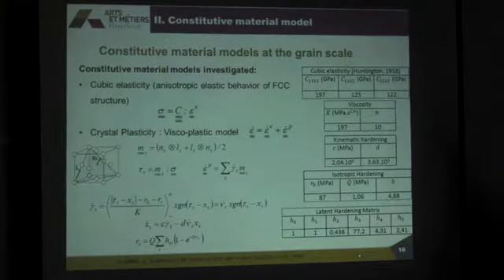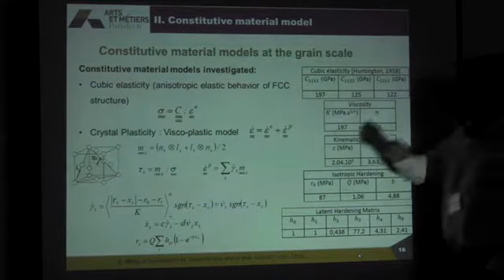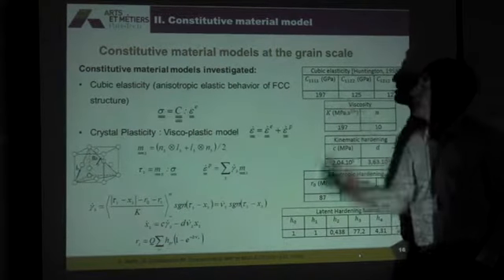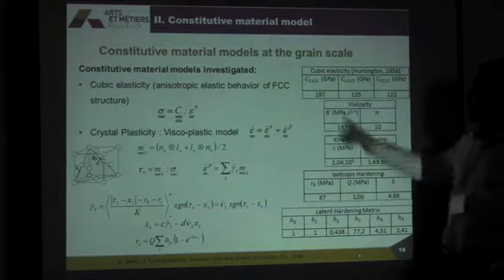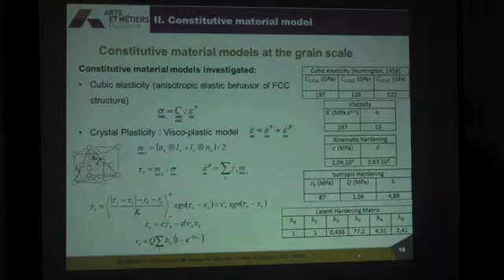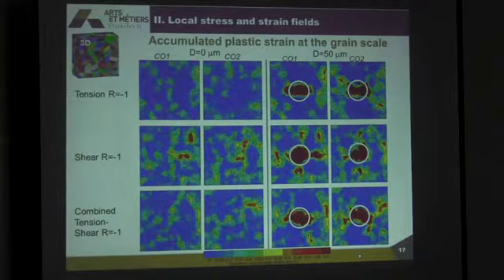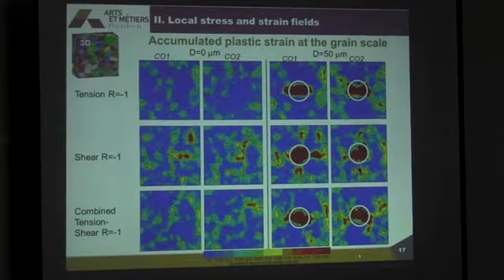Now, about the constitutive equations. We use, for the elasticity, the cubic elasticity of the face-centered cubic crystal — you see here the coefficients. And we also use a crystal plasticity model. Thanks to all this, we can compute different parameters: the accumulated plastic strain, all the different stress components.